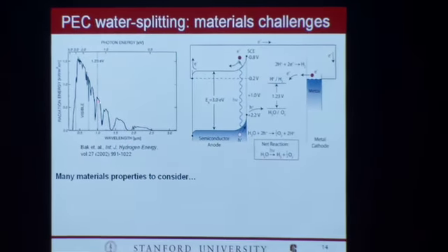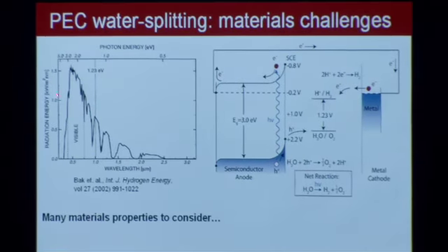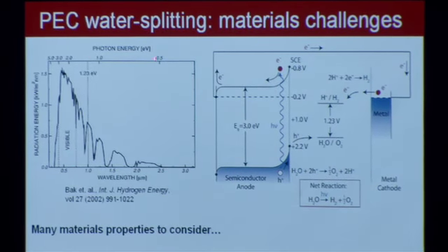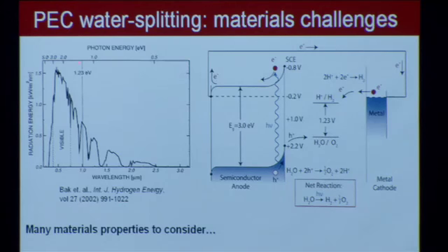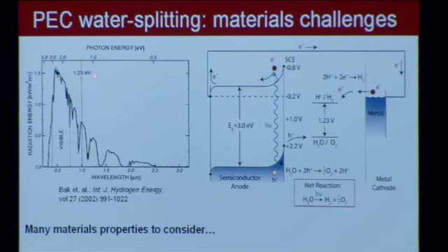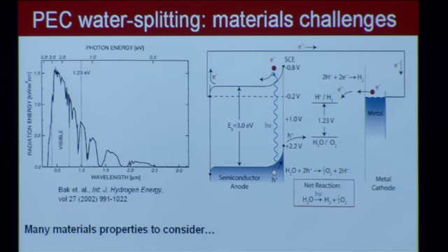The good news is that if you take a look, this is the radiation energy as a function of wavelength or as a function of photon energy. The good news is that here's your 1.23 eV line, right? That's our thermodynamic minimum requirement needed to split water into hydrogen and oxygen. Notice that most of the solar spectrum actually lies in higher energy than that 1.23 eV. So that tells us that we've got a lot of radiation to work with. The question is how effectively can we?